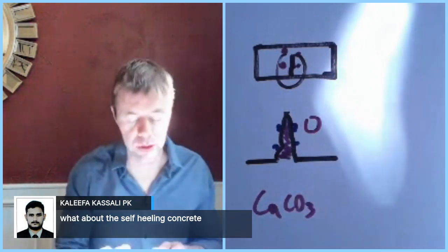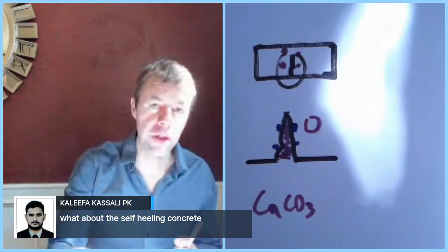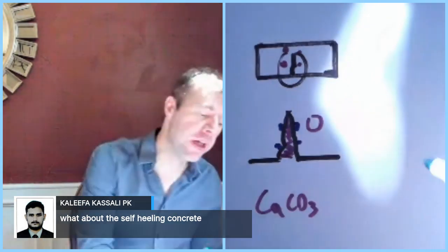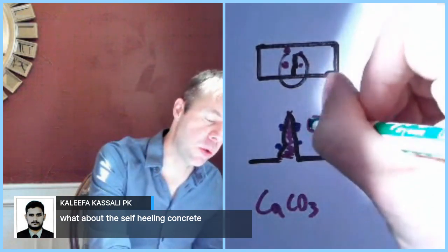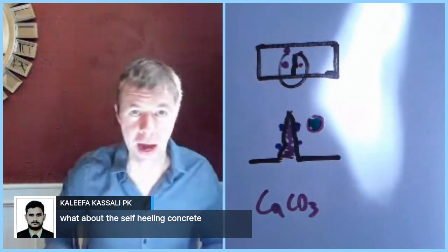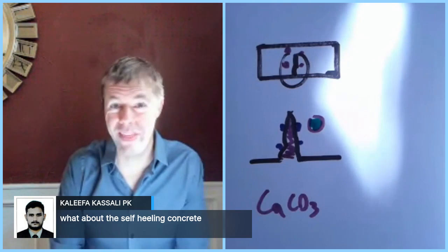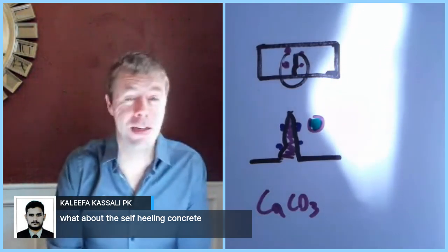It doesn't. And actually, research has shown that it'll fill in those bubbles. It'll fill in the air-entrained bubbles around it as well, just as well as it fills in those cracks. And now you don't have a place for the water to expand to once it starts to freeze. And that's a big deal. You would fill in the crack, but you would lose long-term freeze-thaw durability.